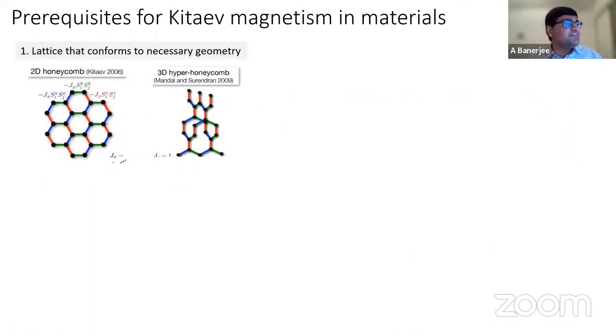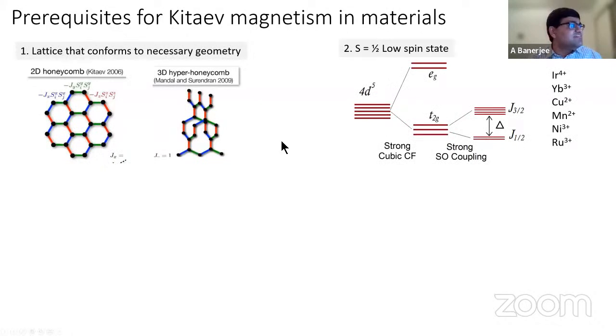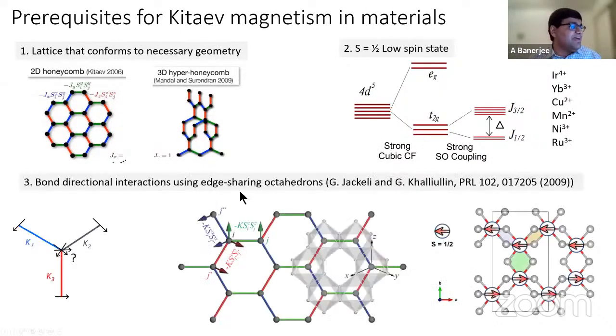So which leads us to what are the material platforms where we see this. As it turns out, there are several material platforms where you see this phenomena. And to get to those material platforms, there is this famous paper by George Jackeli and Giniyat Khaliullin back in 2009, where they showed that in order to get to these Kitaev states, you have to satisfy a few conditions. What are those conditions? First is that you have to have a honeycomb type state, or these Y motifs as we talked about. Secondly, you have to have a low spin half state, and you have to have a strong cubic crystal field and strong spin orbit coupling so that you get to an effective J half ground state, which you get in these kind of ions.